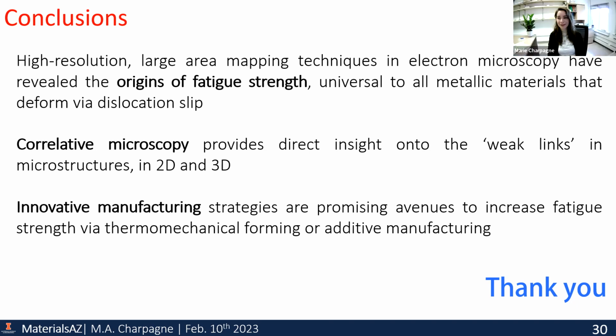That's a very good question. We need to do some more TEM, that's for sure. We haven't looked at this scale, but looking from EBSD, we see that the twin plane is no longer straight, right? So it's geometrically necessary dislocations that came in, and we still have to look at how these dislocations actually interacted with the plane at first. But I think essentially the curvature of the plane is different. So the simplest interpretation would be, it looks like a twin, but it's curved. Yeah. That's interesting. So that would mean it would sort of be compressed on one grain and tensile on one side and compressive on the other side, if it was like that, perhaps. Probably. And how you can picture it after this process is essentially just a random high angle boundary that has a misorientation close to 60 degrees, but that's pretty much it.